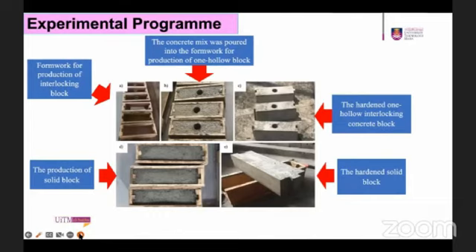After all ingredients had been thoroughly mixed, the fresh mortar was poured into the formwork and compacted to remove air pockets. The fresh mortar was then left to set for 24 hours, and the formwork was then removed. The cubes and interlocking blocks were then cured for 7, 14, and 28 days in a curing tank filled with water. The samples were cured to keep the mortar moist and prevent cracking. Once the curing process was completed for the specific age of 7, 14, and 28 days,